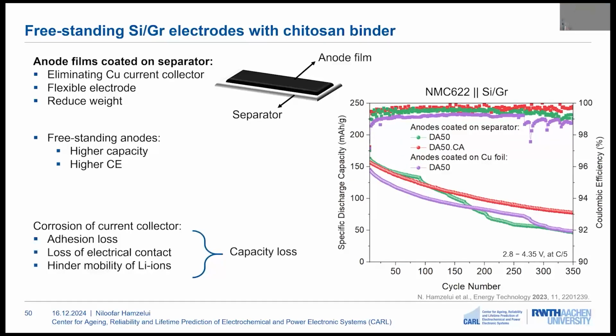And this can be due to the fact that by eliminating the copper foil, we reduce the corrosion and the degradation products that can happen on the current collector, which can result in adhesion loss and a loss of electrical contact, which can result in capacity loss of the cell. Comparing the freestanding electrodes with and without cross-linking, we can see that initially they show a similar performance, but in the long term cross-linking is improving the performance of the cells.